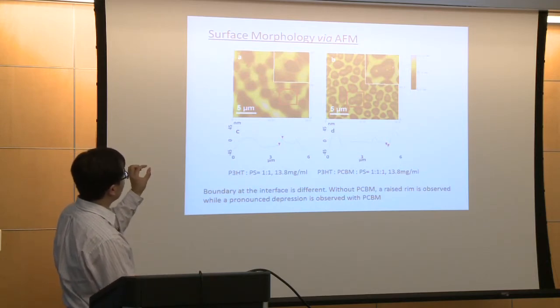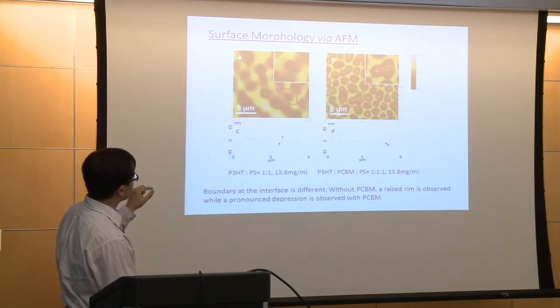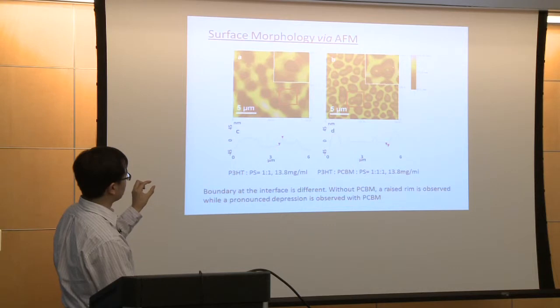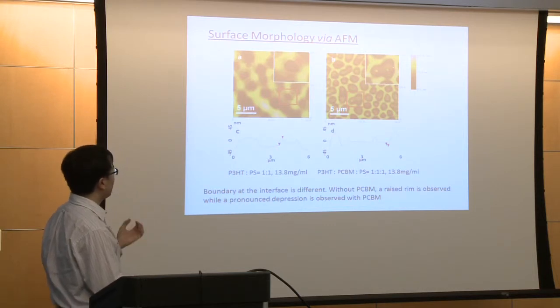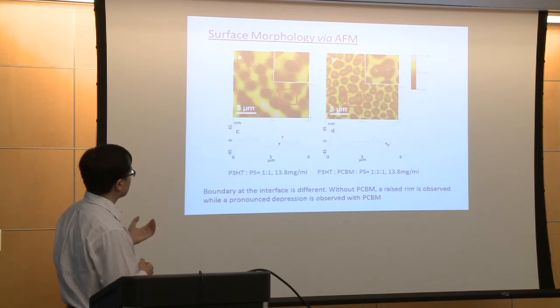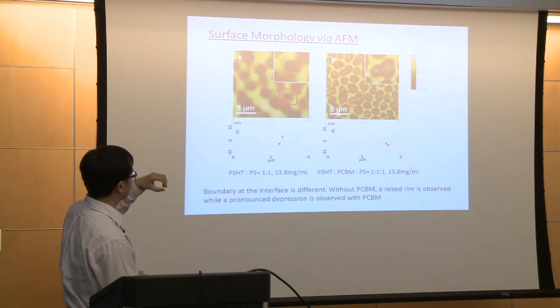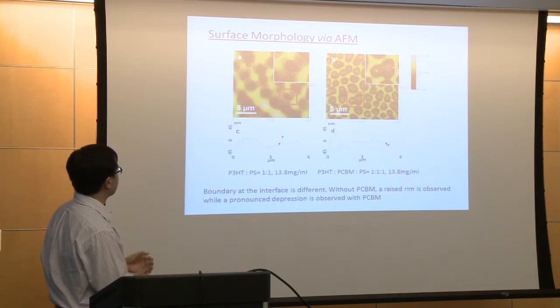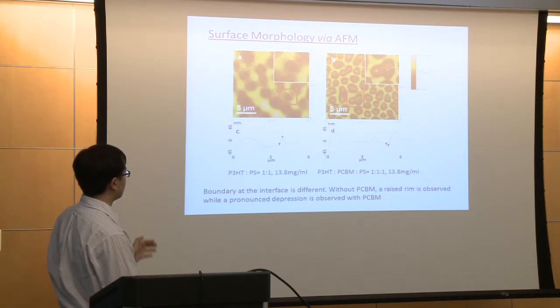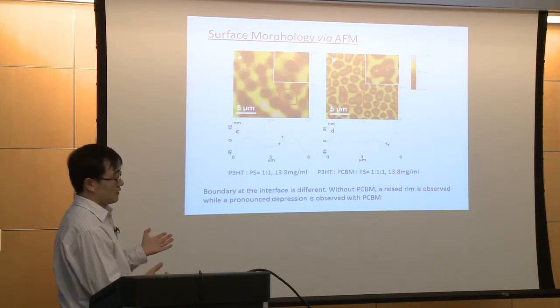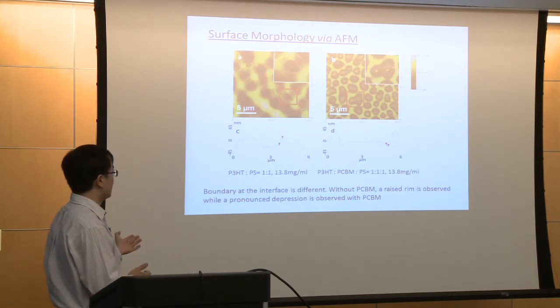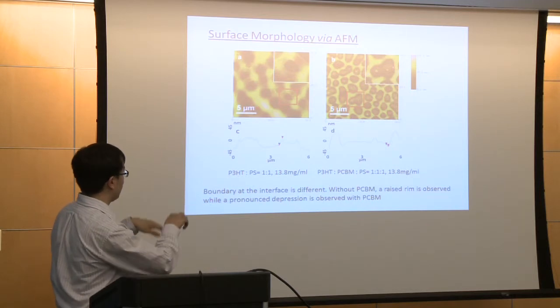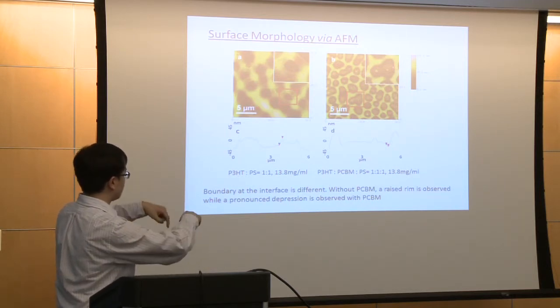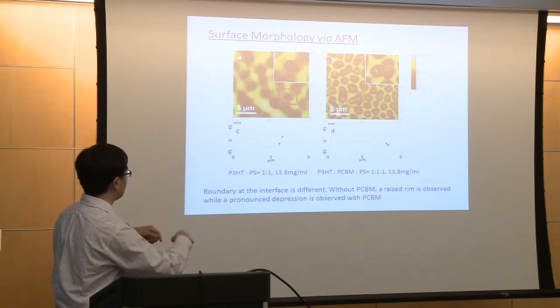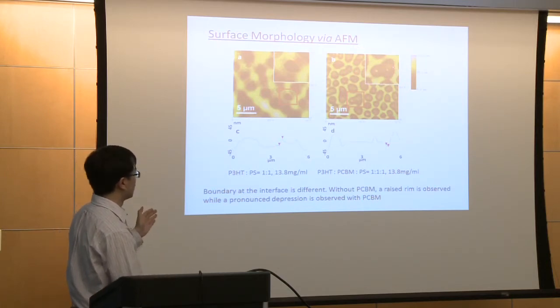You can see a very light ring at the boundary between two materials. In the AFM image, the light part means the higher area, and the dark part means the lower area. Which means there's a raised ring around the boundary at the interface between two materials. And we think that's because P3HT doesn't like polystyrene, so the polystyrene will pile up at the boundary, which makes the boundary higher than the rest of the area. So that's how the raised ring formed here.